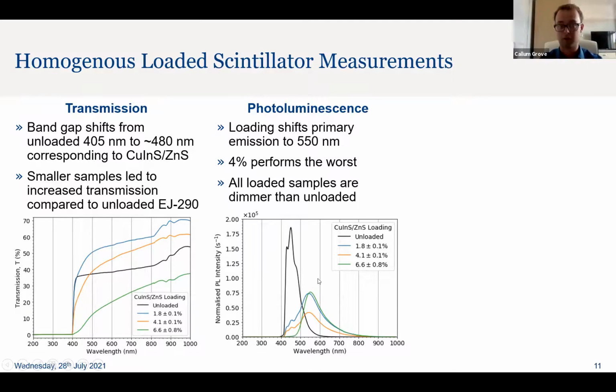Moving on to photoluminescence. We have the unloaded EJ290, which shows a similar emission spectrum to EJ212, which is what the resin itself is based on. And then when we have loaded plastic scintillators, those peaks have dropped in intensity due to being absorbed by the quantum dots, and the quantum dots themselves are emitting at 550. And so we end up with this red shift in emission.